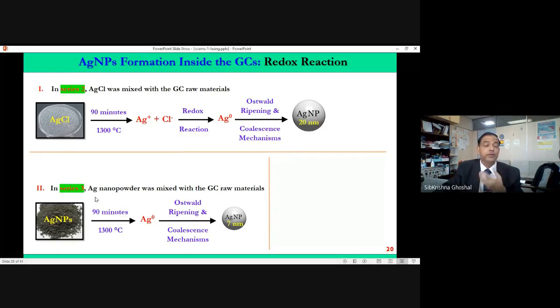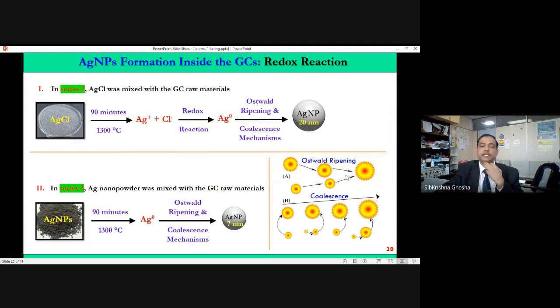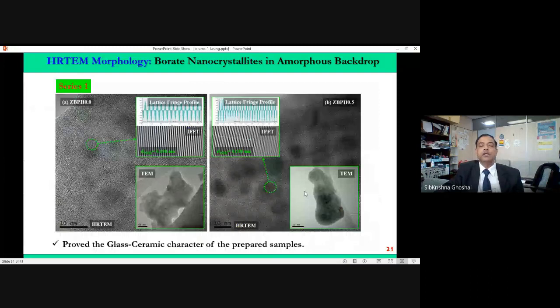But if we start with already pure nanoparticle from the company, again, some of the bigger nanoparticle can form smaller sizes. So basically, the idea is to tune the nanoparticle size. That's it. Because the surface plasmon property of nanoparticle is dependent on the size and morphology. If we can tune them by heat and cool control, temperature control, we can get whatever we want. So this is the process by which this nanoparticle forms, called Ostwald ripening and coalescence. So how do we know that this is really the ceramic?